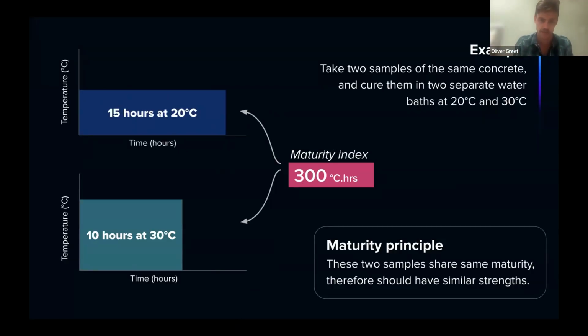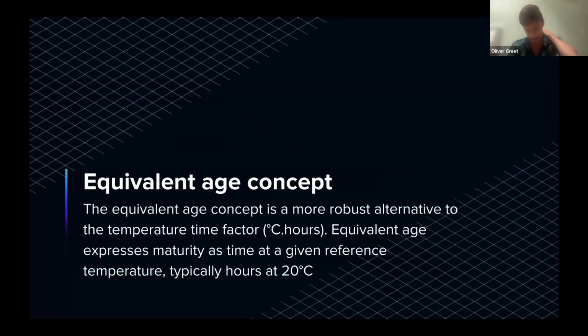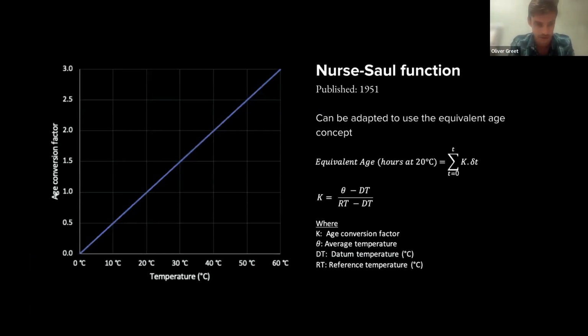What this unlocks is the ability to actually take account of varied temperature conditions as the concrete matures, and also to predict how different thermal environments will influence the rate of reaction. In subsequent papers that were published, they took this technique a lot further, and I'll give you a quick example of that now. So this is the first function that was published, and what we can see here is that at 20 degrees Celsius, at any given time, we're relating the rate of concrete curing to a sample curing at 20 degrees Celsius to understand how it cures and the rate it cures, relatively speaking. So if we look at these charts, we can see at 20 degrees Celsius, that gives us an age conversion factor of 1.0. Now, if you double the temperature using this function, that tells you at 40 degrees Celsius, a sample should be curing roughly twice as quickly as a sample at 20, and vice versa at 10 degrees, half as quickly.